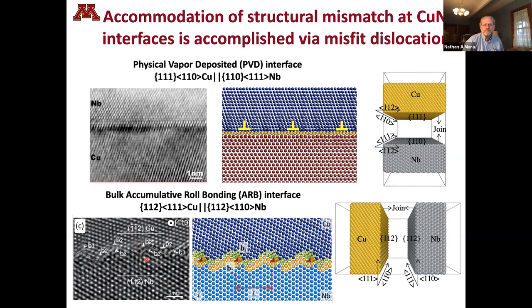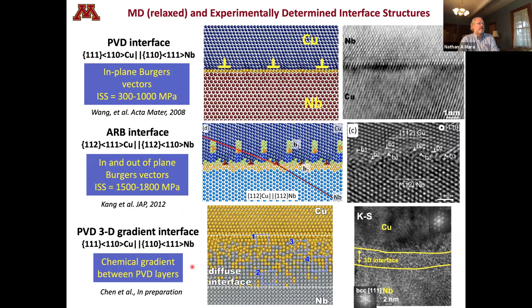So this is what we're going to see here today. We've talked a little bit about the PVD interface, copper and niobium here. We have the 111 planes in copper, and the 110 directions in copper are parallel to the 110 planes in niobium and the 111 directions in niobium. All the Burgers vectors of the dislocations required to relieve the strain mismatch are in plane. So that's one important feature of this. And we have this quantity here, ISS. That's the interfacial shear strength, or how difficult it is to shear one phase relative to the other. We'll see that being an important quantity as well.